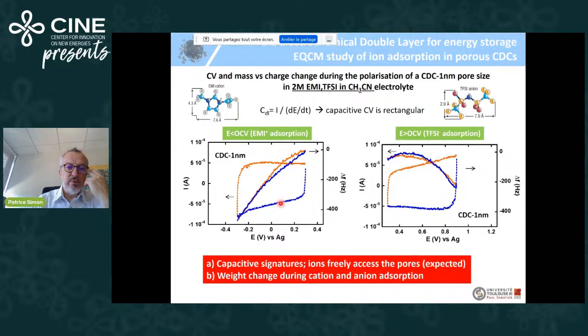And you see you go to more or less constant current here and constant current here. And then you have here a slight change of current because there is a kind of electrosorption driven process. But anyway, we have capacitive signature. And this is here the change of resonance frequency of the quartz recorded during the cyclic voltammetry. And you see that we have a frequency change.